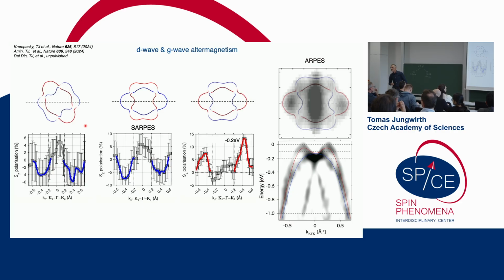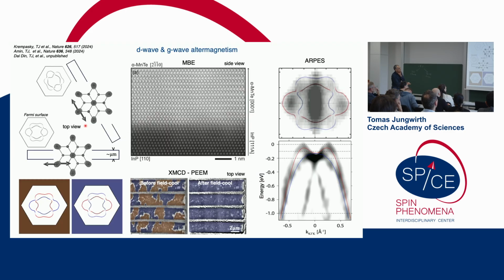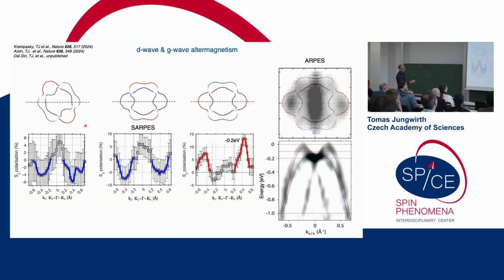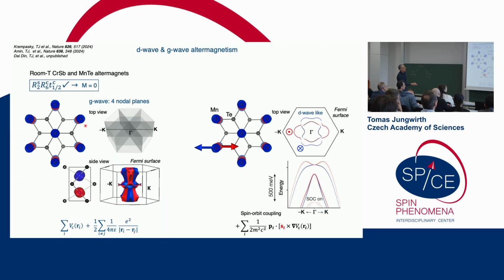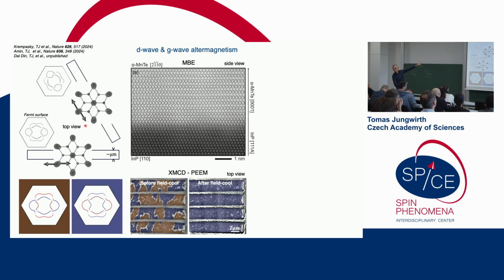Can I ask you, I'm a bit confused, but if I look at any of those pictures, they have 2-fold symmetry and not 3-fold. So you just switch off spin-orbit coupling. That doesn't lower the symmetry. It does, because you have the Néel vector. The Néel vector is in the plane, and the Néel vector lowers the symmetry. And therefore, depending on which of the 3 easy axes you have, you can have 3 different rotations of the Fermi surface, okay?